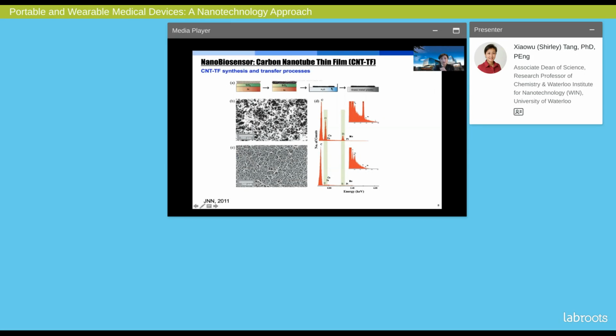It starts with silica particles that are loaded with catalysts, which are transition metals like cobalt and iron. As you can see, after chemical vapor deposition, which is a process, the nanotubes grew out of them. Each nanotube has a diameter of about 1 to 2 nanometers. Those nanotubes grow out of the seeds, which are the catalyst. And we further developed the transfer process that cleans up this nanotube, as shown here, and also allows us to transfer this onto plastic, glass, or certain types of low-cost substrates.